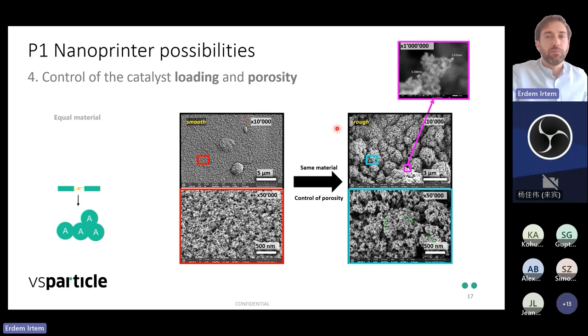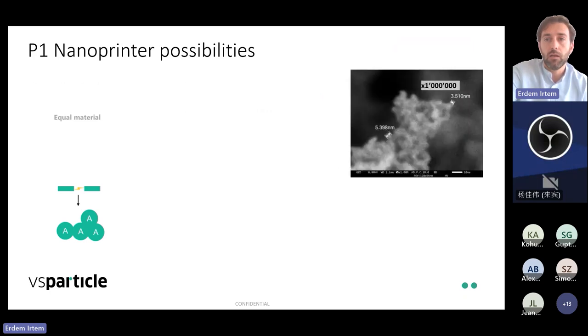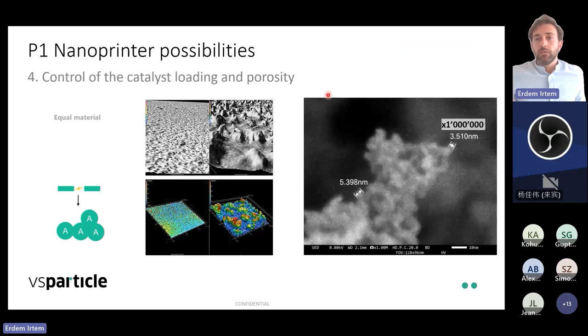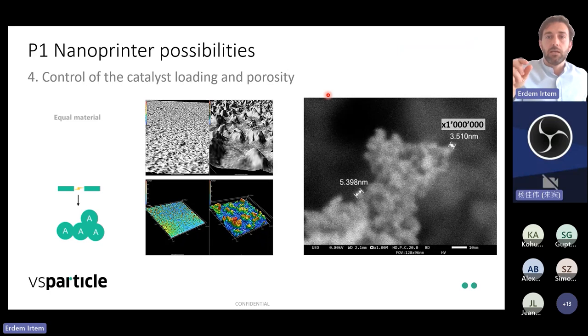But when we play with this distance between substrate and nozzle, at the same magnification here, you see the same substrate, the same catalyst. We can form a more porous, more rough surface, which is quite interesting for electrocatalysis applications or any catalysis applications, to be honest, even for adsorption studies. Again, the advantage is to keep the particle integrity, so you still have the same nanoparticle of the same size.